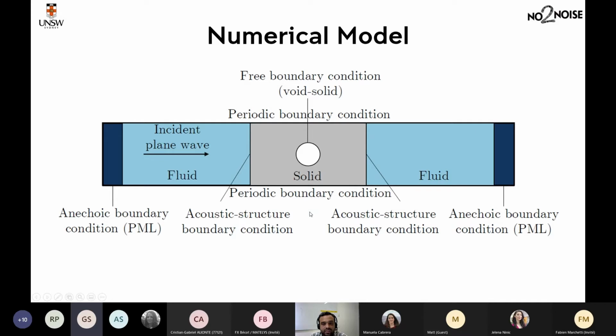And as I said, we have an infinite number of scatterers in this direction, and they're arranged periodically. So for numerical simulations, we use what is called periodic boundary conditions to simulate the infiniteness in this direction. Between the solid and void, it's just a free boundary condition. But if you want to simulate air, which is inside your cavity, you can model your air, and then you can define an acoustic structure multiphysics boundary condition here. Okay, on either ends, we define an anechoic boundary condition.